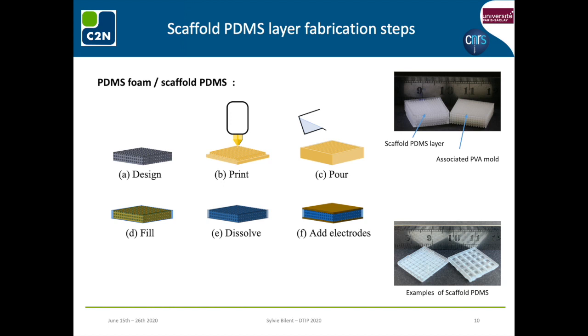PDMS is placed in a stove for 2 hours at 75 degrees Celsius. After curing, the whole structure, PVA mold and PDMS, is soaked in a water bath to dissolve the PVA to obtain the PDMS microchannels network architecture. The resulting scaffold PDMS layer is placed again in the stove for 2 hours at 75 degrees Celsius to remove the excess water. A 16 mm by 16 mm square shaped samples have been produced with various thicknesses and inner porosities. Here are some examples of PVA molds and resulting scaffold PDMS layers.